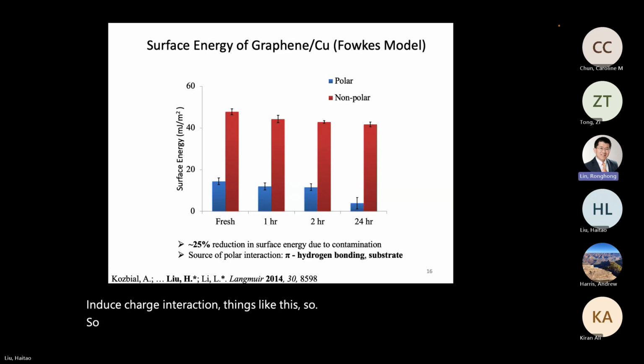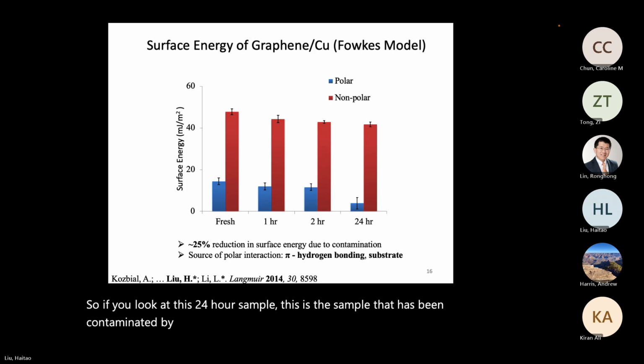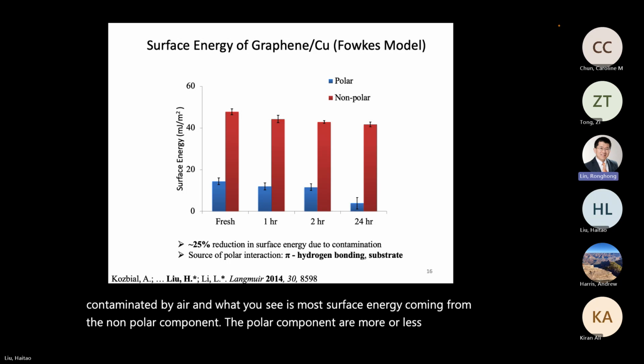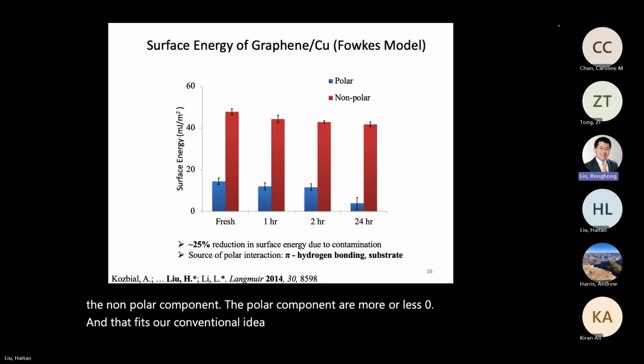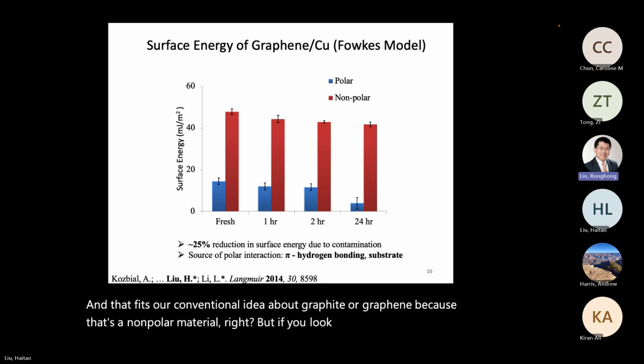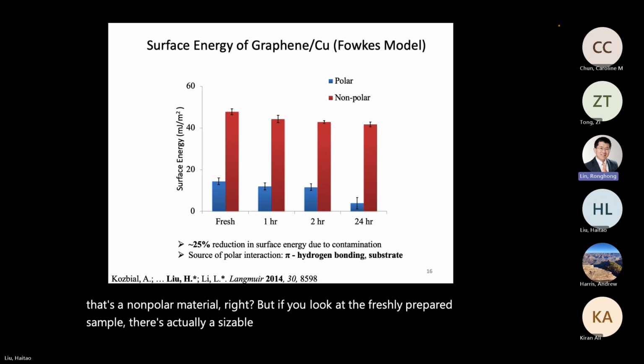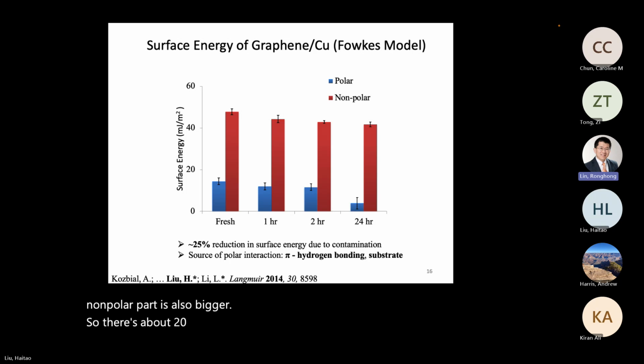So if you look at this 24-hour sample, this is the sample that has been contaminated by air. And what you see is most surface energy coming from the non-polar components. The polar components are more or less zero. Okay. And that fits our conventional idea about graphite or graphene, because that's a non-polar material. Right? But if you look at the freshly prepared sample, there's actually a sizable polar component in it. Certainly the non-polar part is also bigger. So there's about 25% reduction in the surface energy due to surface contamination.